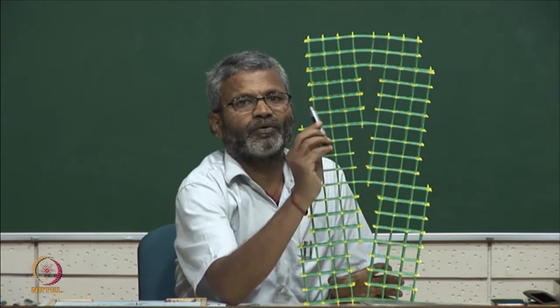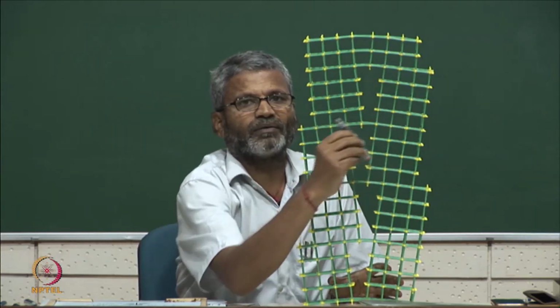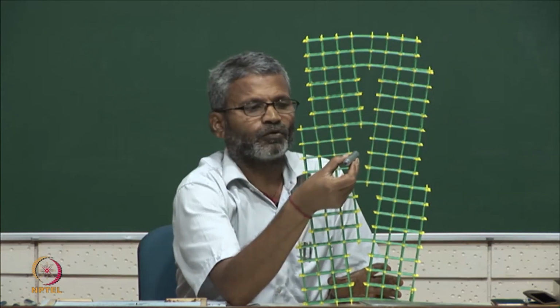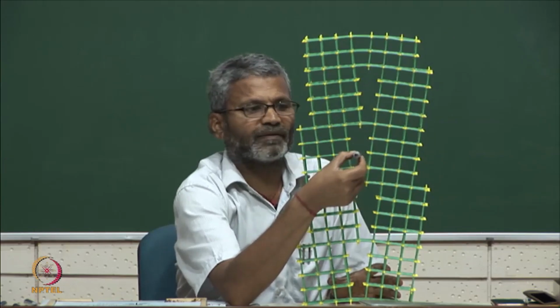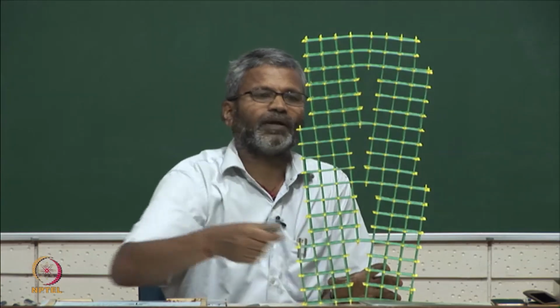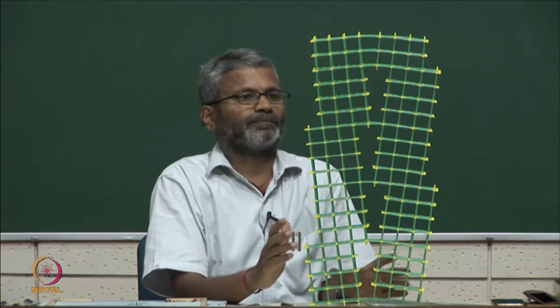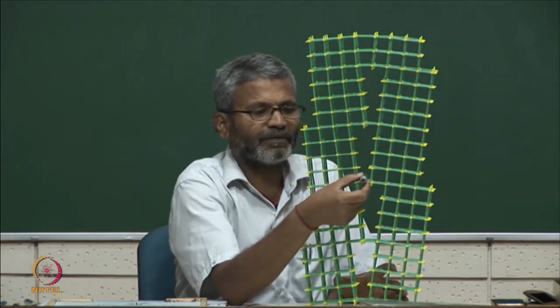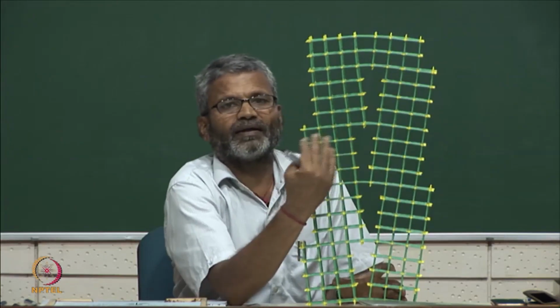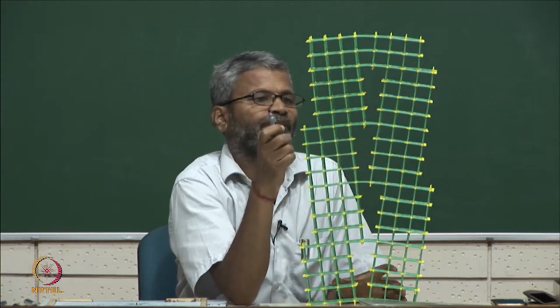About this, if I rotate this crystal from this orientation, I can get into this orientation. So, this horizontal axis is lying in the vertical plane. So, this is a tilt boundary, and about the tilt axis the two grains are equally tilted. So, this is a symmetric tilt boundary.